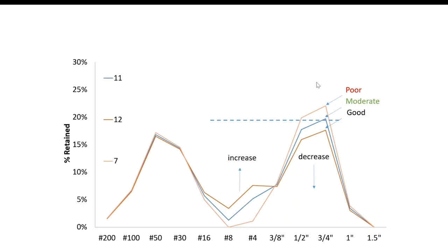Tyler, on the commercial side, on super flat floors, they're pushing the larger aggregate for shrinkage. We're going to have some great shrinkage data for them, Gary. What I've seen so far, there's no difference in shrinkage between the larger aggregate and the smaller. And you say, whoa, how is that possible? What shrinks is the paste. And if the paste is the same between the larger and the intermediate, the shrinkage is going to be the same. Make sense? Makes sense.